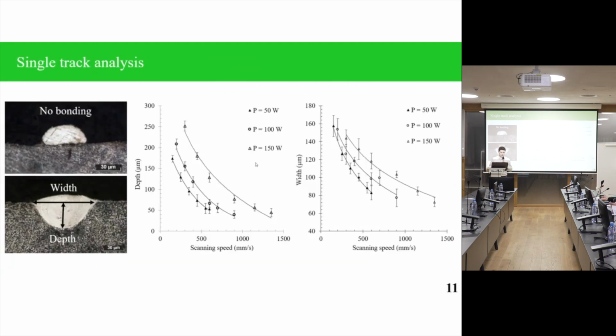And the first step of the experimental study involved single track analysis. At this step, the substrate was lowered by 1 layer thickness. The powder was deposited, and then it was remelted with a single laser passage. During this analysis, some process parameters were already excluded as they do not provide enough remelting depth. For other cases, the melt pool dimensions were measured, namely the width and depth of the melt pool. This data will be used further.